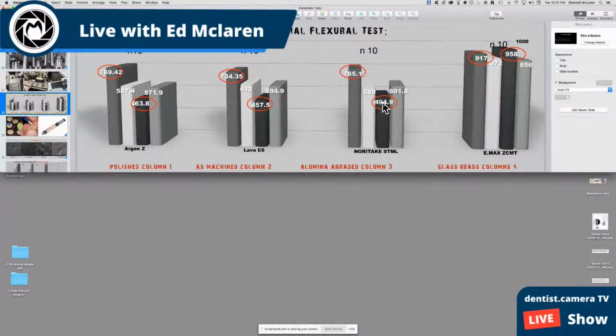Now, here was the interesting thing. Let me go back to this for just a second, okay? That if we sandblast, so this was sandblasted, and then if we sandblasted and resin coated the surface, that simulated bonding, and then we fractured them. So if I was going to use a 4Y material or 5Y material, I'm going to bond it. I'm going to do adhesive dentistry because the strength went back up to 600 megapascals.